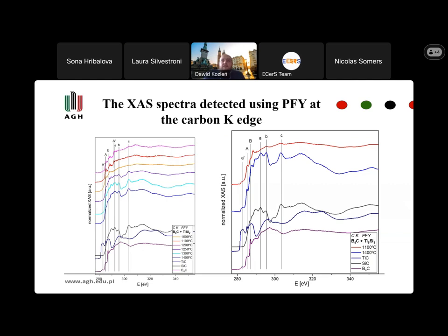This is the result from the synchrotron line in the EXAFS spectral line. And this line was very interesting to compare with the results from the XRD measurements. Because in the XRD measurements, even at the lowest temperature, close to 1150 Celsius degrees, we show that we have phases like titanium boron silicon carbide, but still they are not well homogeneous. So we can compare these results with this spectral line in the synchrotron Solaris with my colleague Rasha, and we compared that this method can support analyzing ultra high temperature ceramic materials, how well they are synthesized.